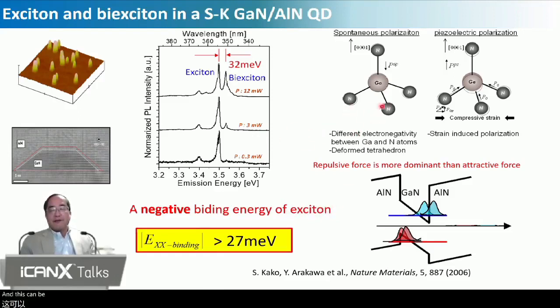And this can be explained by the built-in electric field due to the spontaneous polarization and the piezoelectric polarization. In this case, we cannot avoid the built-in electric field inherently formed in the heterostructure. So because of the quantum confined Stark effect, the electrons are pushed to this side, and the holes are pushed to this side, even if two electron hole pairs or the bi-exciton is generated. So the repulsive force is more dominant than the attractive force. As a result, we see the negative binding energy.